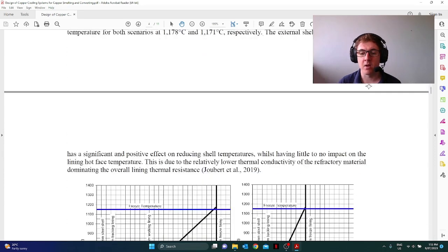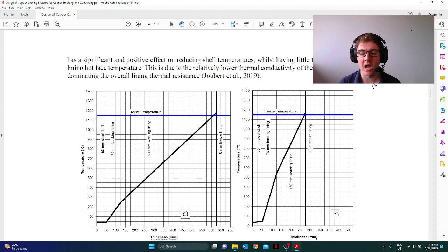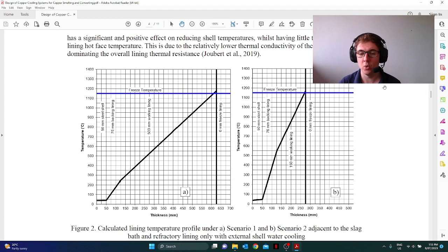The next scenario is, what if, rather than having just a bare steel plate, you cool it with a water cooling system? Looking at the maths, if you go through the 1D heat transfer stuff there, you can see that this steel plate, when you put water on it, does not change too much between the start of your furnace campaign and the end of your furnace campaign. So that steel plate temperature is lower, but doesn't change.